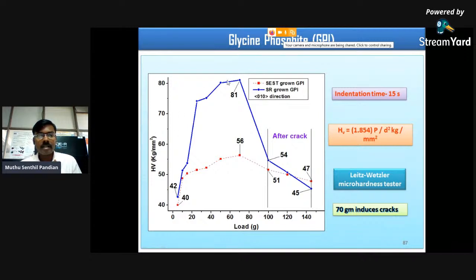So this is again for glycine phosphite single crystals. This blue indicates the SR method, and this red indicates the conventional method. The crack reduction is higher in the SR method because of the higher mechanical stability. The reduction of the micro cracks appearing in the SR grown crystal is high. I will explain in the next few slides with the animation.